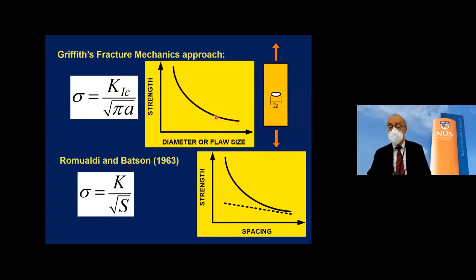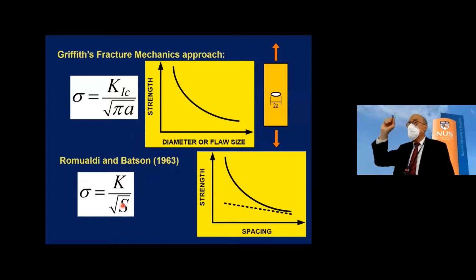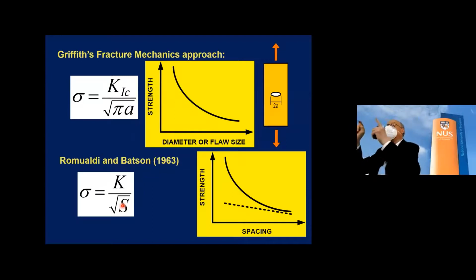When the cracks decreased, the strength increased significantly. So it was very, very fine glass fibers. The strength of that fiber was much higher, according to the relation, than if the fiber diameter was bigger. So you could say Romualdi and Batson used the same idea. They picked up a constant, and instead of using the crack size, they used the spacing of the fiber. In their mind, the crack goes between one fiber and the other and is arrested there. It's not going to go anywhere.